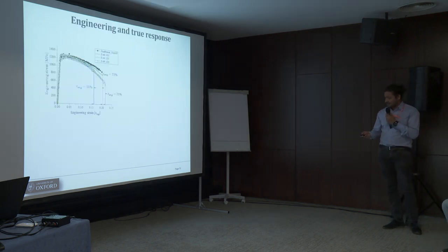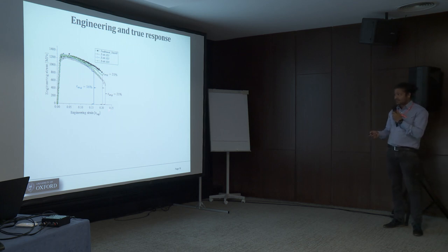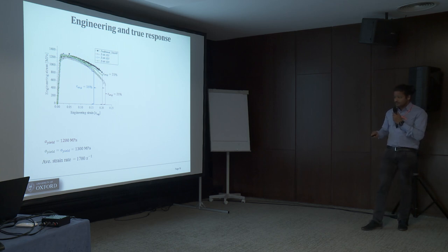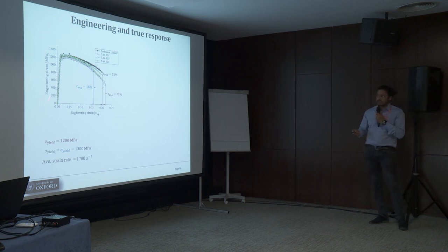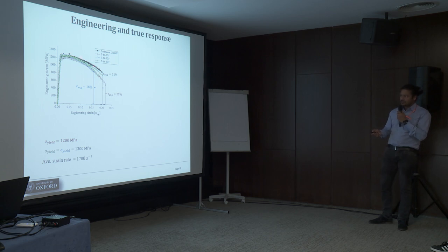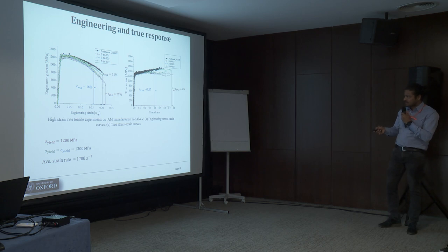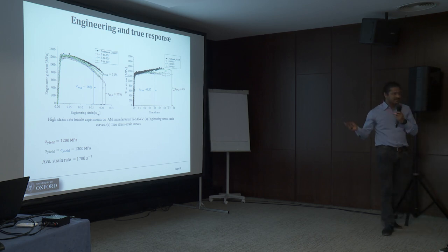Here we also found that the D2 direction shows less ductility compared to the other two directions. Moreover, direction 1, which was laid down horizontally, shows slightly softer behavior compared to the others. One interesting observation is that the additively manufactured alloys also show a softening behavior compared to traditional or conventional Ti-6Al-4V. We managed to estimate the true response as well, which confirmed the results we obtained in the quasi-static conditions. With this understanding, we now want to better understand the material behavior further.